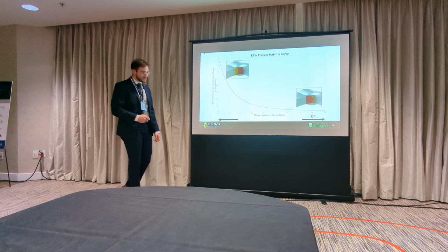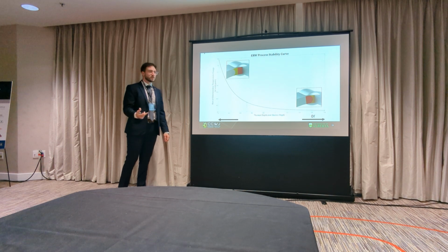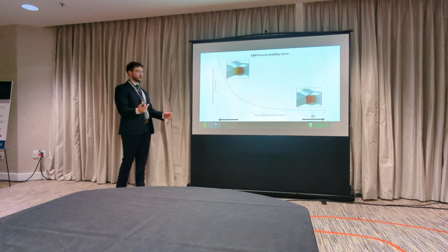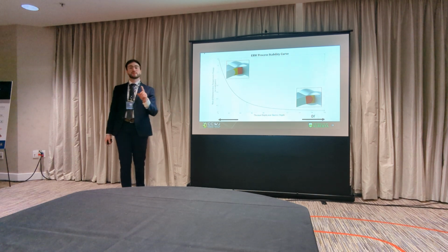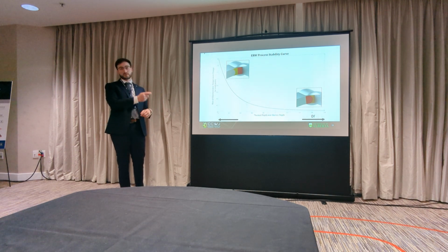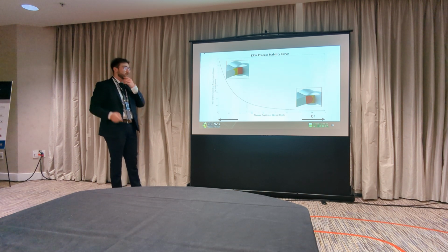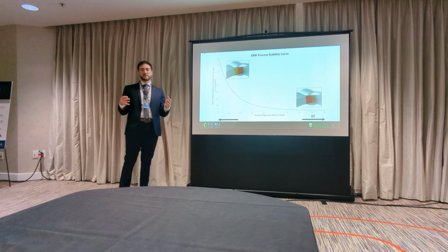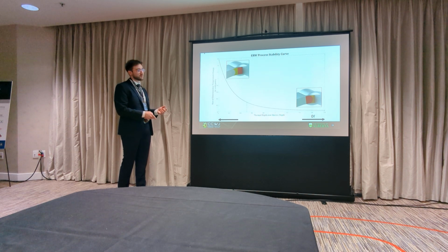What does this mean? In the ERW process, the V length, the frequency, and the mill speed change sometimes. The mill speed and the V length are usually fixed constant for large scale analysis, but the frequency bumps a lot. We saw those waveforms earlier in the presentation, with the frequencies going up and down by about 3 kilohertz to 5 kilohertz. Those bumps can lead to a change in V temperature and V stability. So when we're in the electric regime, we have more of our weld metal that's being dominated by current. So a bump in frequency is going to affect more of the material. So here we're less stable, here we're more stable. This is the thermal mode over here.